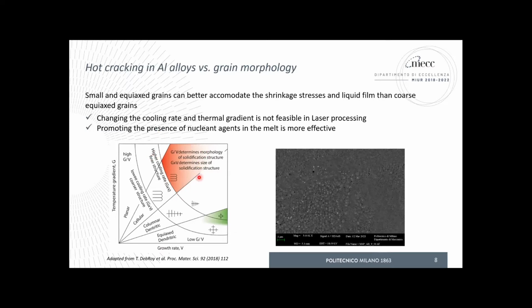And the red region here corresponds to the usual condition for laser beam additive manufacturing. We have quite a large temperature gradient and quite large growth rates, so that we produce a structure which is very refined, because both parameters are very high in value, but we also tend to get columnar grains. There are studies in the literature trying to modify parameters in order to move out from here, but my opinion is that it becomes very difficult to change the conditions so much while still using a laser. A laser intrinsically produces very fast solidification and very high growth rate. But it's very difficult to modify parameters.